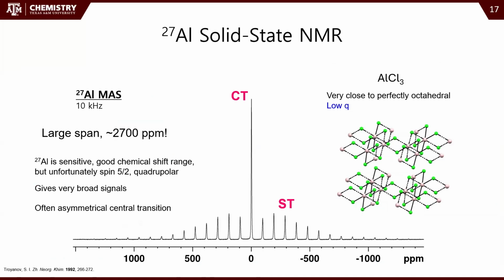So I started with just 27 aluminum NMR of aluminum trichloride. And this is a nice octahedral aluminum, so it should have a very symmetric electric field gradient. And we see the span is still almost 3,000 ppm. So it's pretty large compared to the phosphorus. And we have lots of rotational sidebands, even at 10 kilohertz of magic angle spinning. And the signals are kind of broad too.